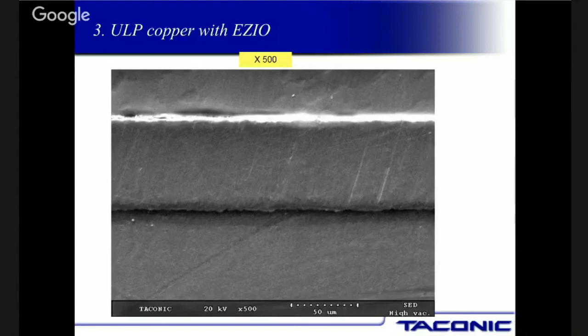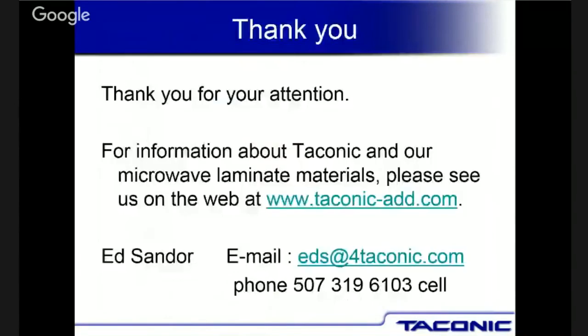When you look at Teflon material, our material is a thermoplastic, which means that as you heat it up, it gets softer. And so the amount of stress in a plated through hole is significantly reduced because the modulus of our material at room temperature versus IR reflow temperatures is like 1/100th of the value. It drops significantly. So our material softens, and the copper in the hole actually drives the reliability of that hole. On FR4, the stress goes right to the copper because the material is so stiff, and it actually takes the copper and stretches it, where our material will actually conform to what the copper's doing.